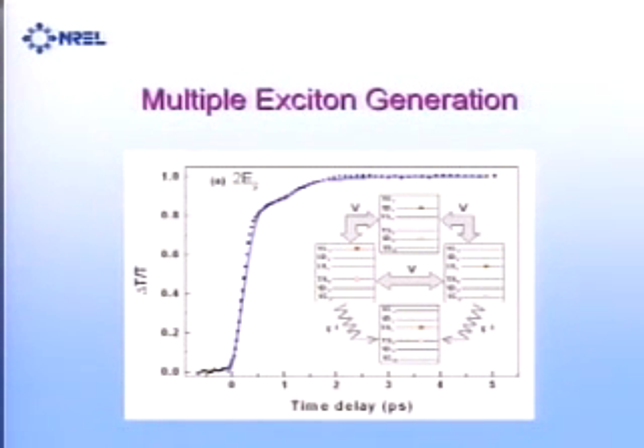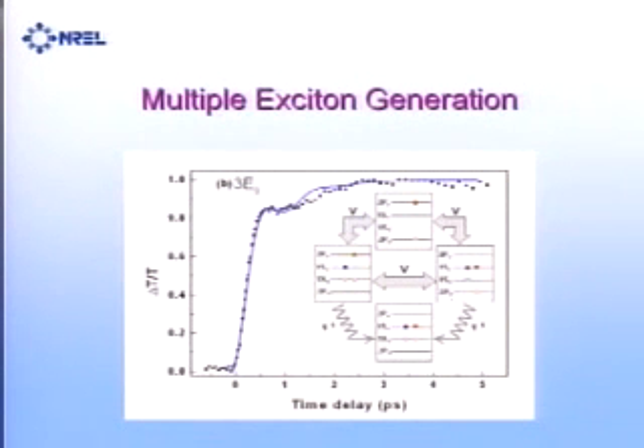oscillation that's produced by the quantum beats at twice the band gap, and this shows the oscillation, which is deeper, at 3 times the band gap. In the case of 3 times the band gap, you have 4 equivalent states that oscillate, and what determines how many excitons you're left with is the dephasing, which of these states undergoes dephasing through phonon interaction. This state, having an asymmetric charge distribution in the dot, will have a stronger coupling with the phonons.